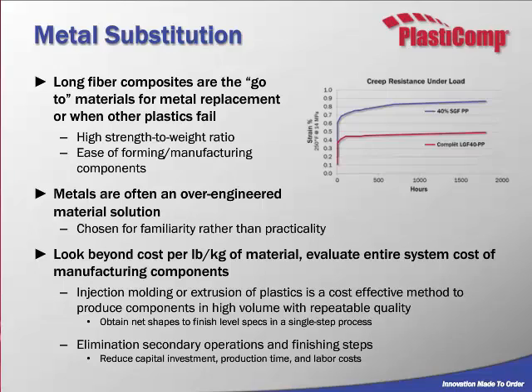And I know that's an immediate rejection point when we talk to some companies, but once we've discussed with them the advantages of converting to a composite part that can be injection molded, and discuss that we can eliminate secondary operations, we can consolidate parts, there is no need for welding or stamping anymore. If you're painting, we could potentially eliminate the painting process by putting different surface coatings on the tool, which will then transfer to the part. We can pre-color materials so that you can avoid painting with the pre-colored compounds. And then in the case of trimming with some cast materials, we can produce a net shape so the trimming